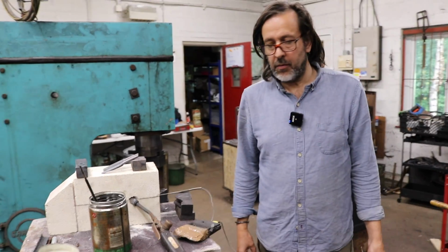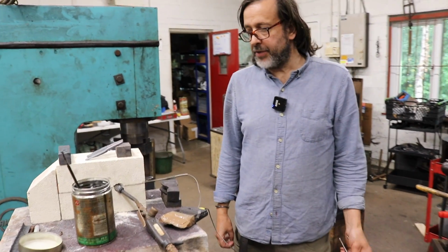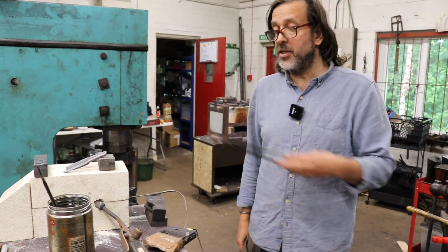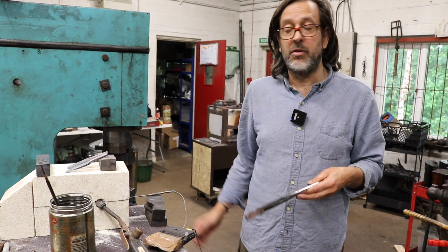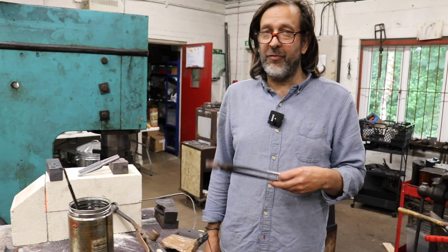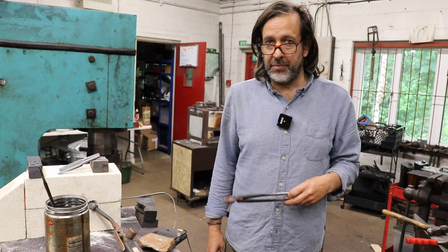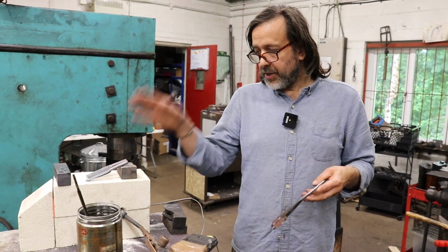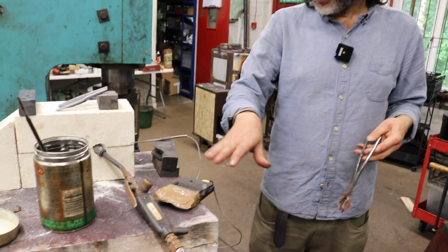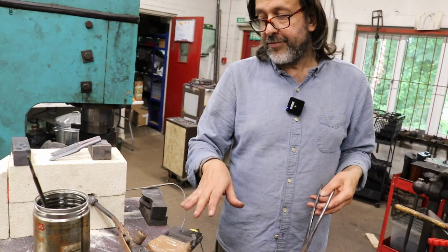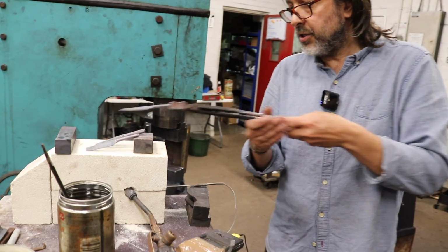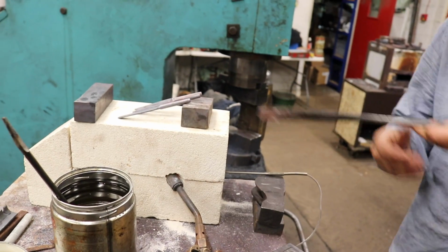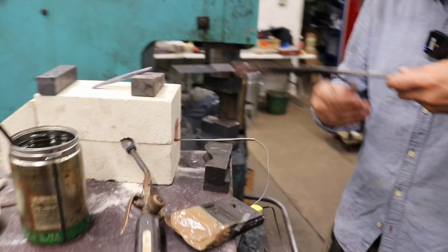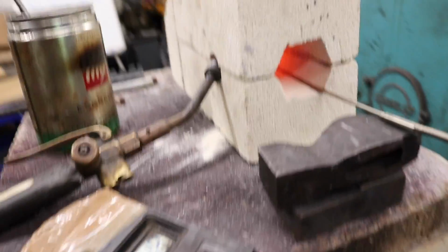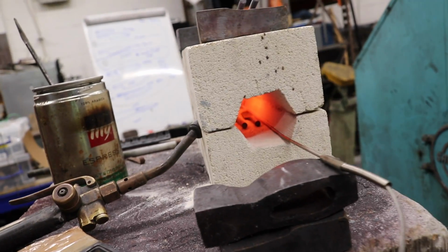So Nick, have you completed 3 normalising cycles then? Yes, we've done the 3 cycles, and the blades are now staying straight. They're heating up and cooling down, which gives me high confidence that at quench they're not going to warp, but we'll see. The forge is slightly overshooting, it's at 850, so I'm going to put another 2 in, and this is going to be for the final heating cycle, which will include quenching. So these are now in, and you'll see the temperature will drop a bit as we put 2 cold blades in.